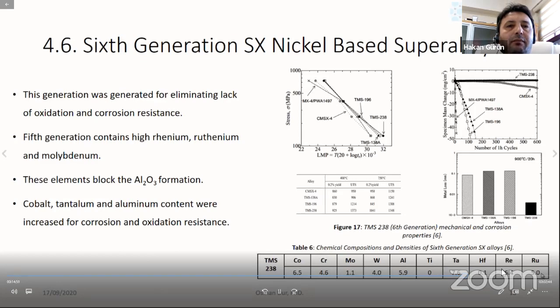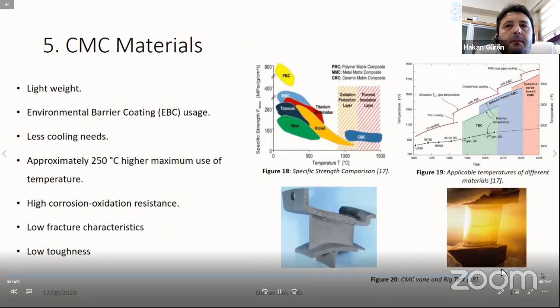the other generations. Ceramic matrix composites are the newest technology in the sector for hot section blade and vane applications. These materials' densities are 3 times lower than nickel-based superalloys, approximately 2 to 2.5 grams per cubic centimeter. These materials are better for toughness than ceramics. Because of the CMC materials' own properties, less cooling is enough. Also, this can be the main reason for the increasing turbine inlet temperature. Turbine inlet temperature increase directly supports the performance of the aero engine.